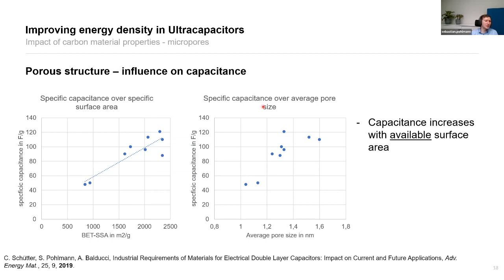So you would say that if you increase the surface area, you most probably will get an increased capacitance, and you're right about that. We did this together with Andrea Balducci from the University of Jena, who has been working on supercapacitors for quite some time. We did this test where you use different carbon materials with different surface areas, using the BET surface area method, and measure the capacitance. You get a correlation: higher surface area, higher capacitance, but you get some outliers as well. So it's a correlation, but not a very straight one.